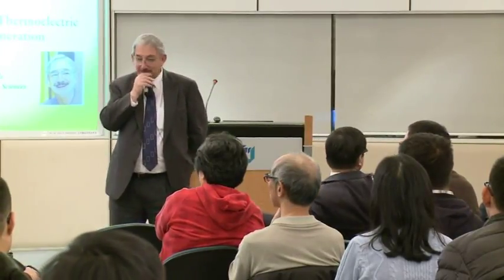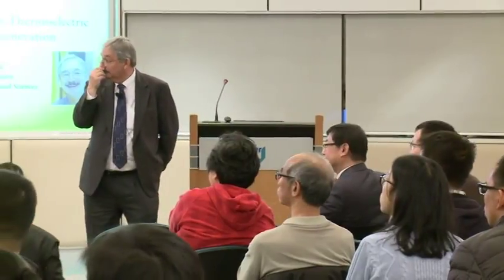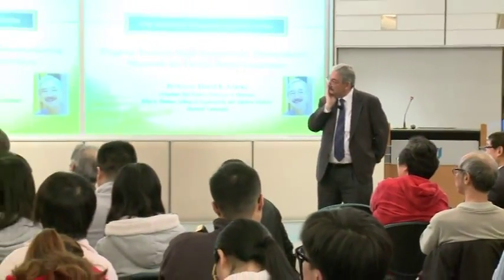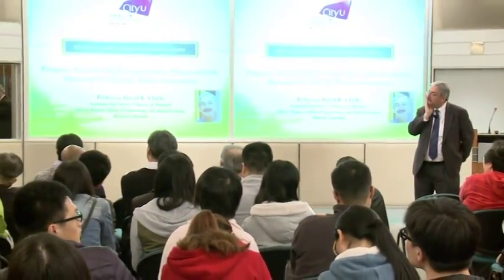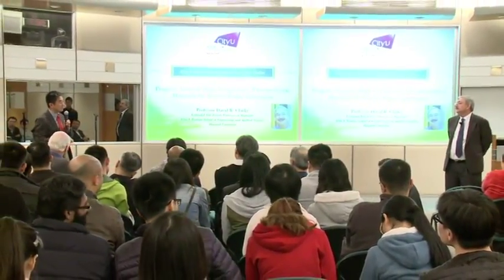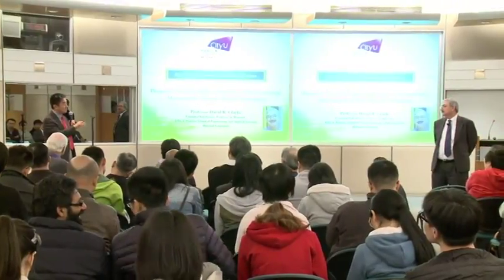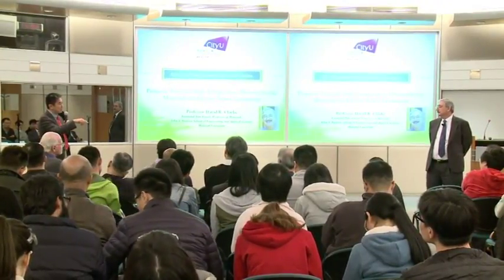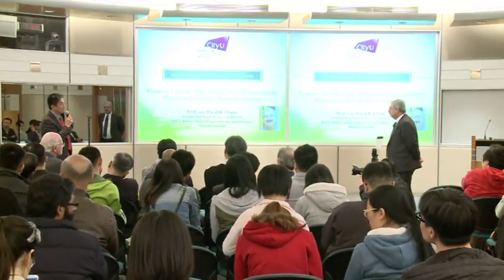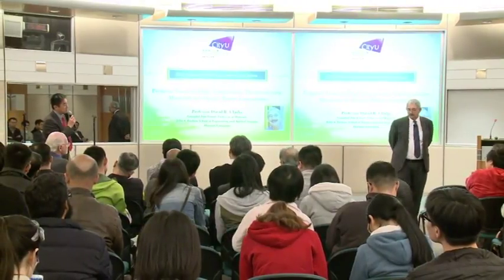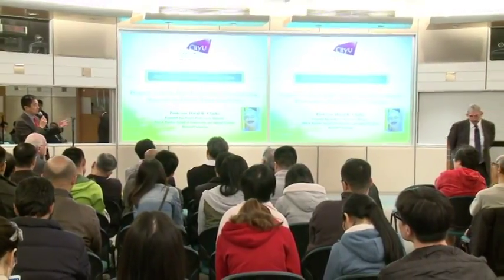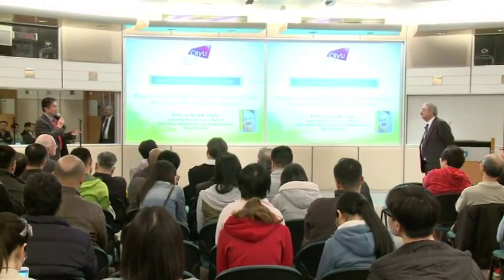Okay, thank you. So maybe a related question. You mentioned nanostructured materials. It seems to me it's a double-edged sword. On one hand, nanomaterials will give you much enhanced phonon scattering, therefore dramatically reducing the conductivity. On the other hand, you have interfaces that also drop the conductivity. And thirdly, at high temperature diffusion can become a problem, and then the material becomes unstable. Do you have any comments on how to optimize this nanomaterial structure?